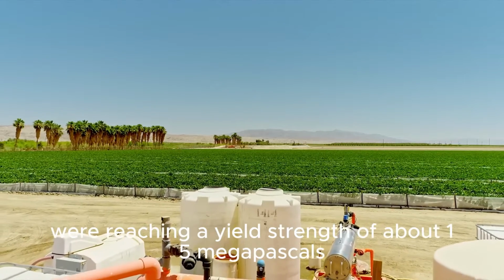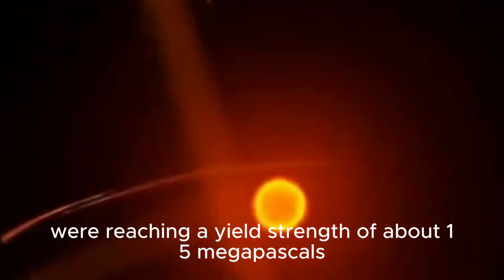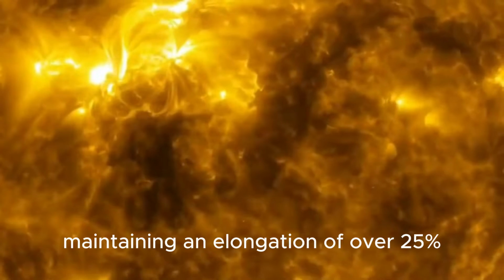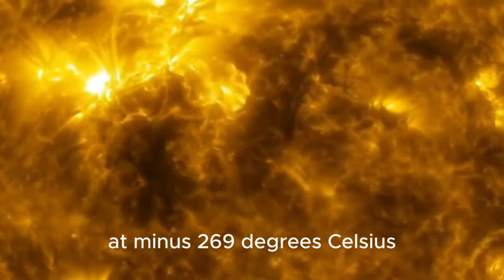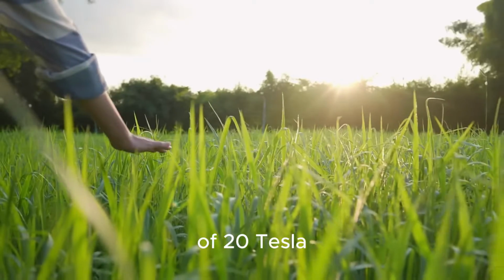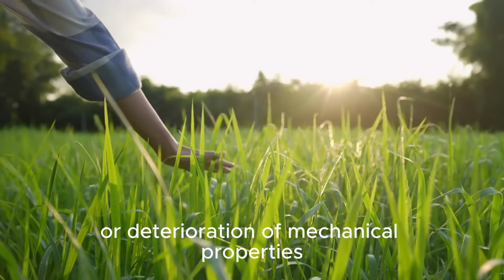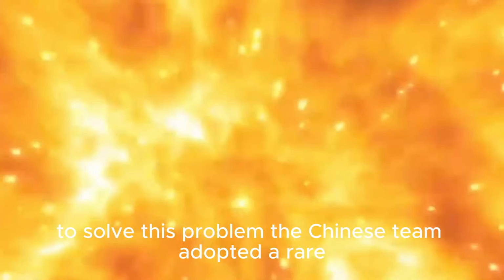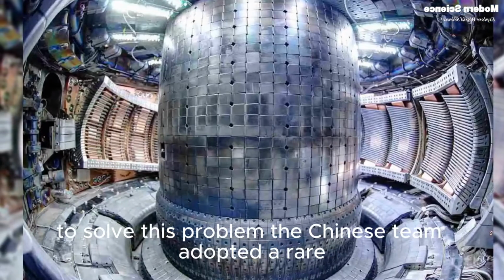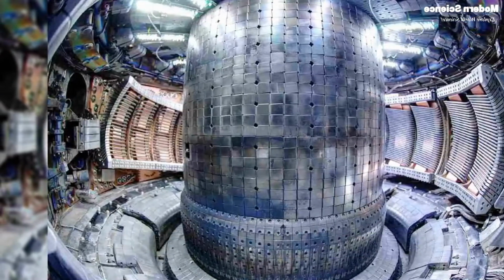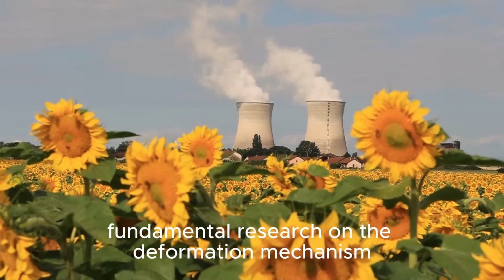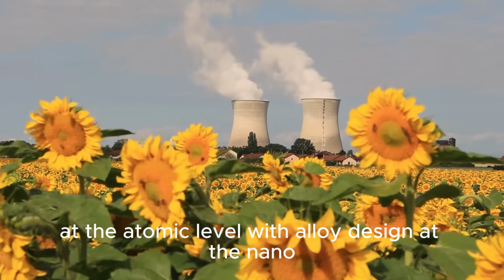The three technical requirements set for the research team were reaching a yield strength of about 1,500 megapascals, maintaining an elongation of over 25% at -269 degrees Celsius, and ensuring the ability to withstand a magnetic field of 20 Tesla without deformation or deterioration of mechanical properties. To solve this problem, the Chinese team adopted a rare materials development strategy, combining fundamental research on the deformation mechanism at the atomic level with alloy design at the nano-micro scale and continuous testing on industrial scale samples.